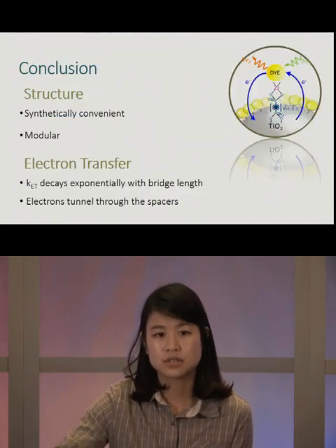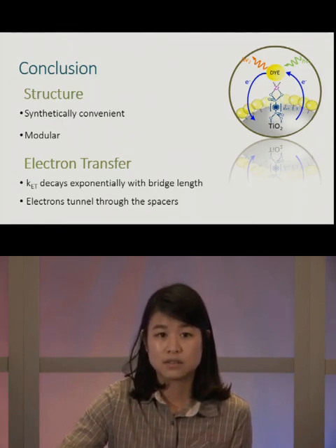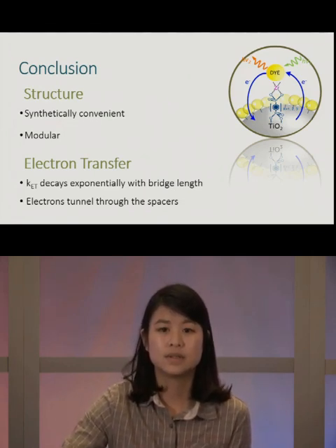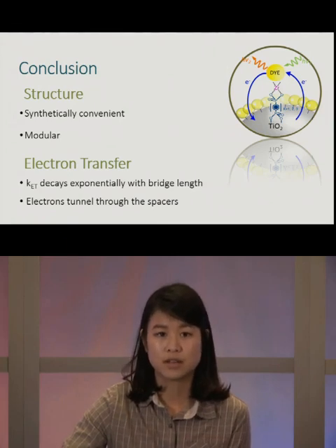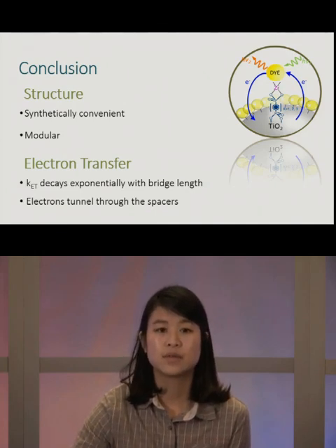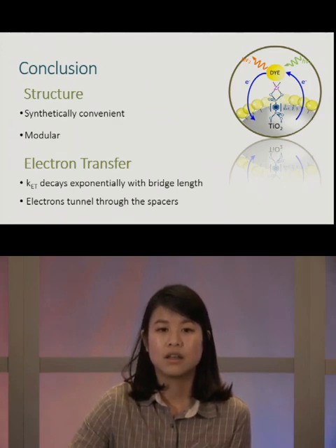So in conclusion, structurally, the self-assembled bilayer is synthetically convenient. Also, it is a very modular technique, which for future studies is very simple and convenient if we want to substitute the dye molecule or the bridge molecules. And for electron transfer rate, the rate, both forward and backward, shows an exponential decay as the bridge lengths increase. And this exponential decay suggests that the electron transfers are lying within the tunneling regime, and further details can be